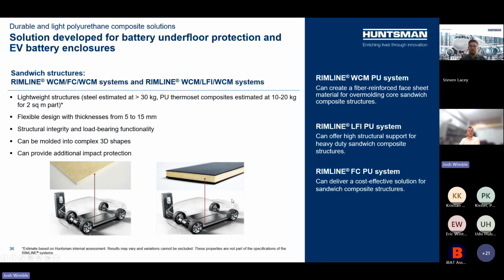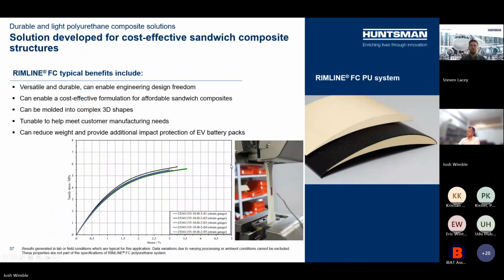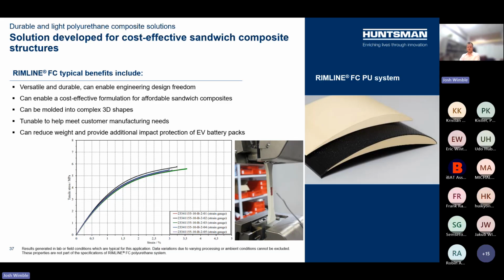Now, wet compression molding can create a fiber reinforced sheet material for overmolding the core sandwich composite structures. LFI offers a high structural support for heavy duty sandwich composites. And then foam core, which we'll talk about in a second, can deliver a really cost effective lightweight solution for sandwich composites. So this here is an example of our foam core, between two skins, if you will. The foam core is ideal for extremely lightweight structures. You're going to go a little bit thicker, but you get extremely lightweight, cost-effective structures. It almost is just offering an air gap between the two skins for excellent impact energy dissipation. With its strong compressive strength at 130 degrees C, this foam core can be widely used in state-of-the-art molding processes without damaging the core material as you press it to different shapes at elevated molding temperatures.